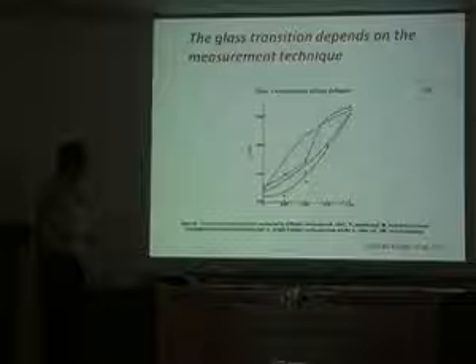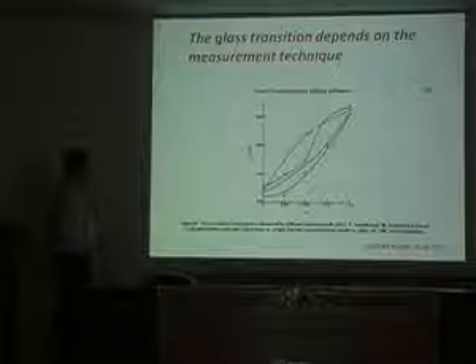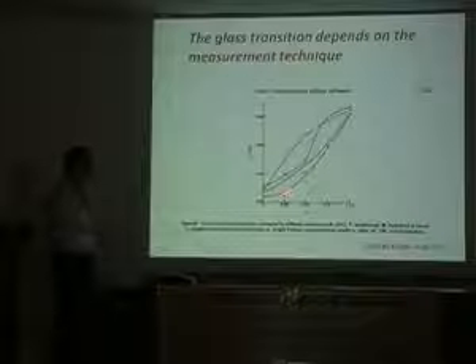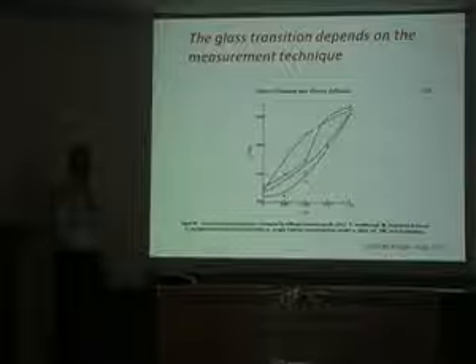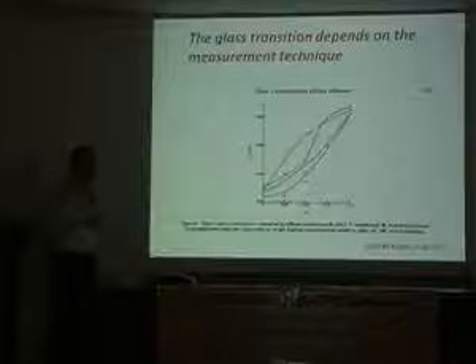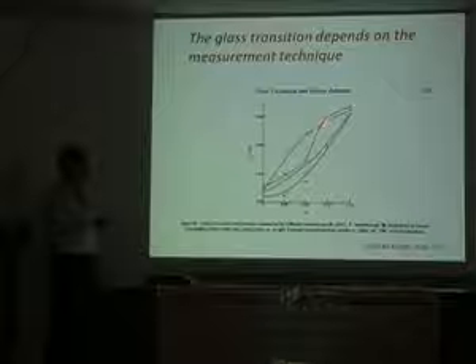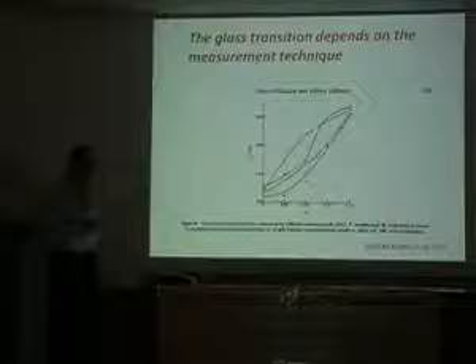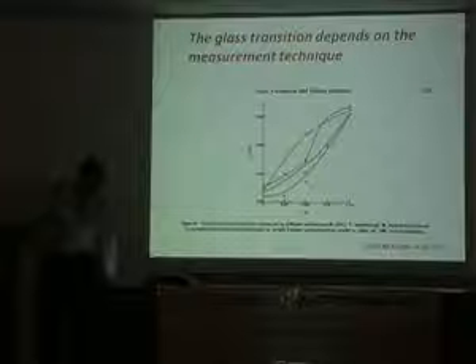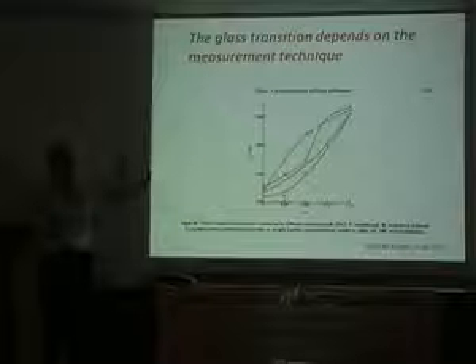To what extent is that because of the time scale? Well, these are probably all measured at more or less the same time scale, 1 to 10 degrees per minute. But the dielectric was probably measured at a higher frequency, but it could all be 1 hertz or 10 hertz, right? It doesn't have to be that high a frequency. But the point is just that you can have a difference depending on how you do it, and the details, again, you have to look at.